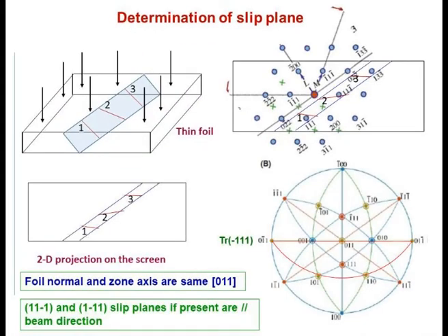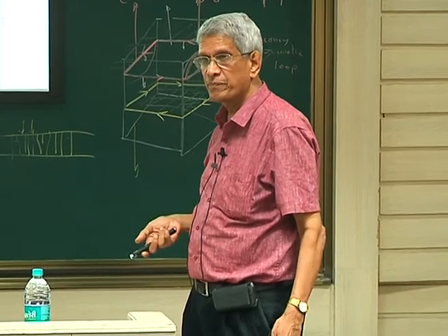But this is where microscopy comes into the picture. From the same region where we have got the image, we have got the diffraction pattern. Since it is an electromagnetic lens, some rotation between the image and the diffraction pattern will be there, because an electromagnetic lens gives a rotation, whereas in optical lenses it's only 180 degrees. Here it is an angle different from that. When we introduce this, we can superimpose and find out the direction in which this trace is lying, the direction in which this projection is lying.